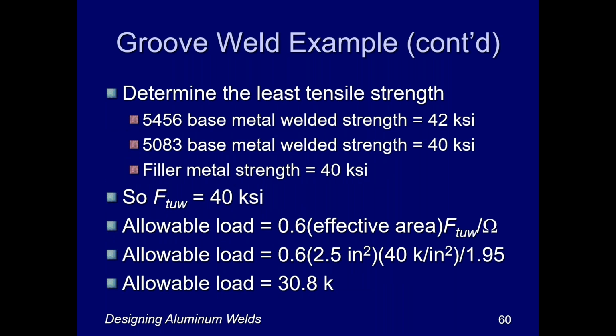Now I need to determine the tensile strength, and for the base metal on the 5456 side, that's 42 ksi. For the 5083, it's 40 ksi, looking those up from the tables. For 5183 filler metal, that's 40 ksi. So the least of those three is 40 ksi. And now I'm going to be able to calculate my strength.